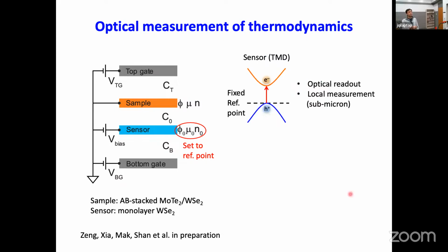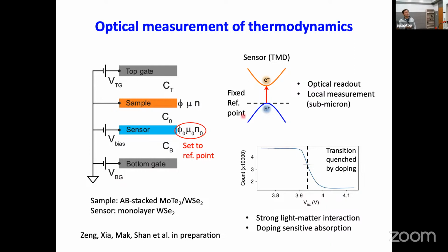So what we do here is we replace our sensor with a monolayer of this semiconductor, and instead of using transport to read out the chemical potential, we use optical means. A natural reference point for this two-dimensional semiconductor is to keep the Fermi energy exactly touching either the conduction band edge or the valence band edge. We shoot light onto the sensor and look at the absorption or reflection contrast, at this particular interband transition in the sensor. Once you push your Fermi energy by applying the backgate voltage to just near the band edge, you can see that suddenly the reflection contrast of the material exhibits a very sharp step-like function. That provides us a very nice reference point: the middle of this step corresponds to when the Fermi energy is located just touching the band edge of the system, okay?